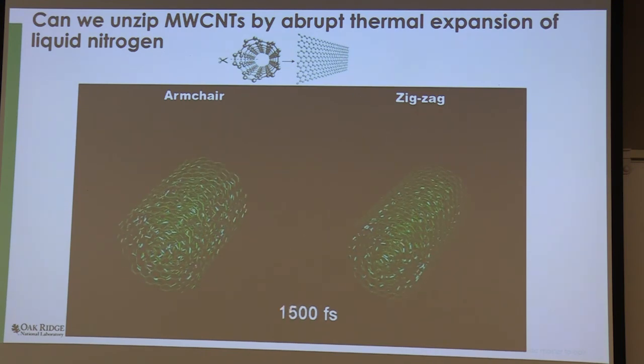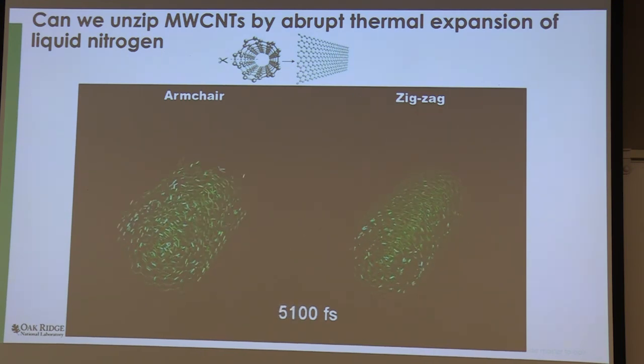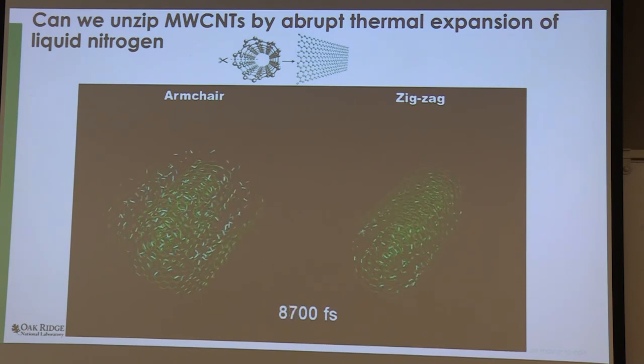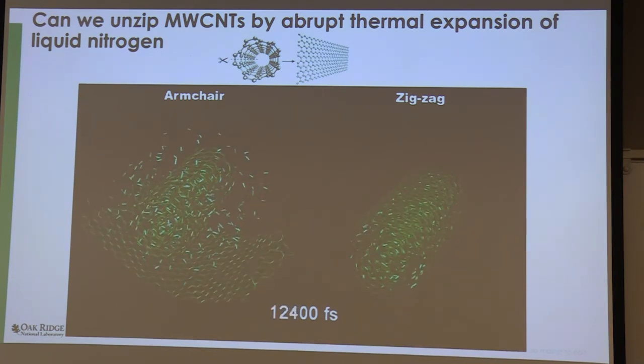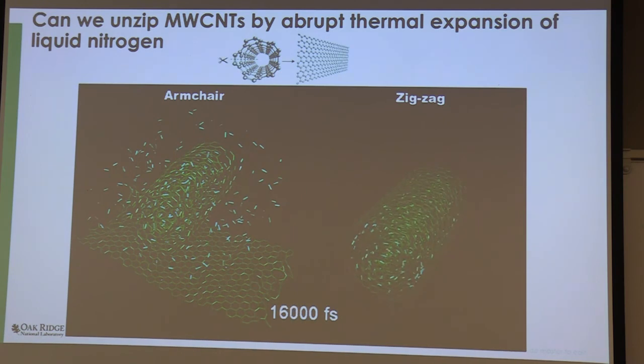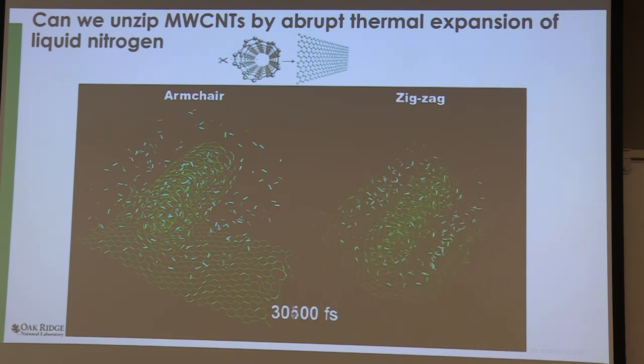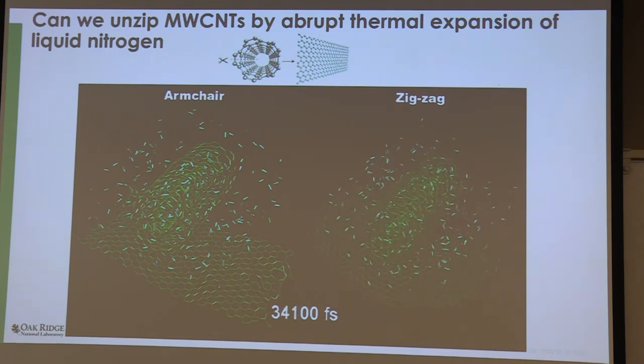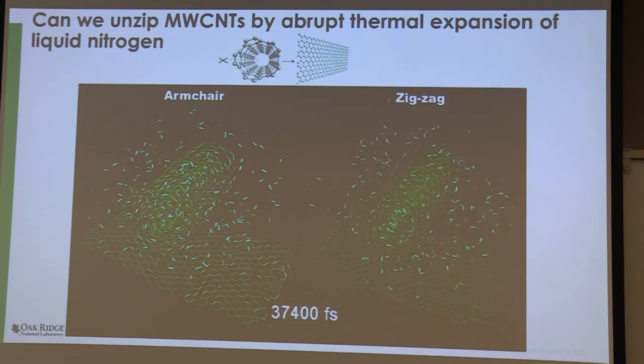And if you do that, what happens is the pressure builds up to a very extreme situation, enough to break a chemical bond. Actually, there are topological defects that occur in this thing, and these take about 5 eV. So it's huge energies, but this is a very local scale, so you're able to do this. And experimentally, they were able to actually do this in the lab and produce these graphene nanoribbons. So you notice there's lots of weird things that happen here at the edge, and that's, again,